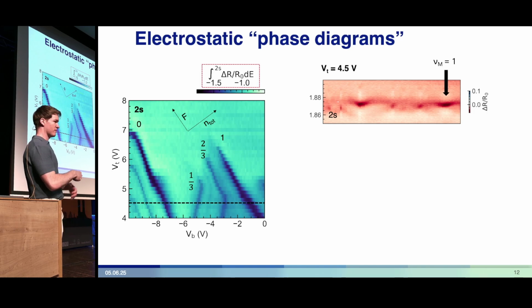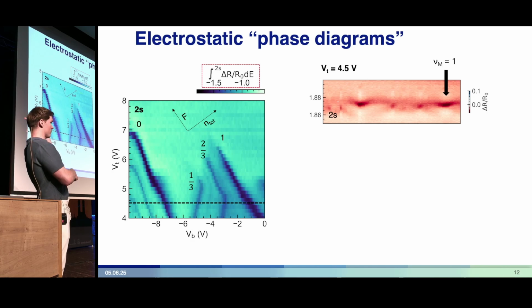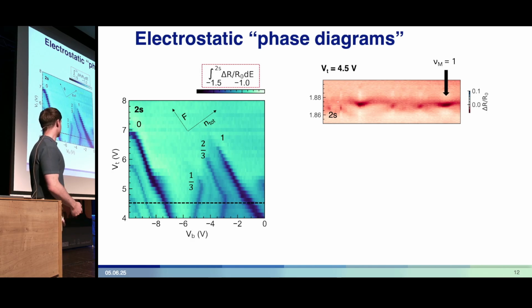These arrows are just a guide to the eye. In reality, the electric field and charge density have rather complicated dependencies on back gate and top gate due to correlation effects and also contact performance. But generally speaking, as we go towards the diagonal, we increase the density, and as we go towards the anti-diagonal, we increase the electric field.